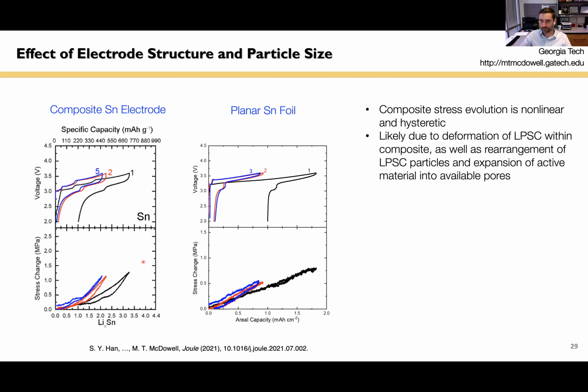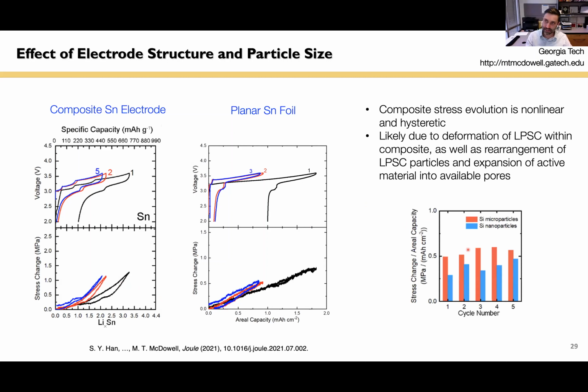Very important. We also found that the size of the active material particles in the composite affects the overall stress change quite a bit. So we did a direct comparison between silicon microparticles and silicon nanoparticles, and there's a lower overall stack pressure change when you use the smaller particles. And this, again, is because we think the expansion of the smaller particles can be effectively accommodated by excess void space more easily than the larger microparticles. And so this is some of that data here. So basically, these experiments helped us to understand some of the details of how the electrode structure can affect stack pressure evolution.